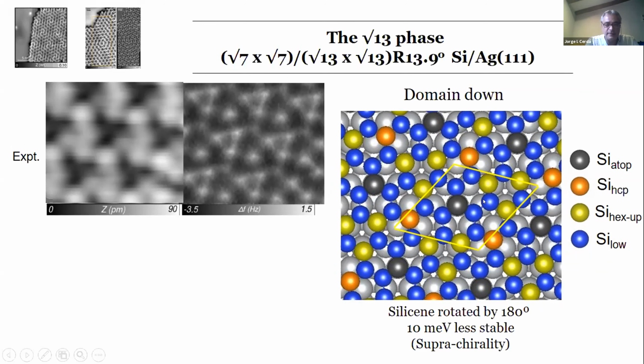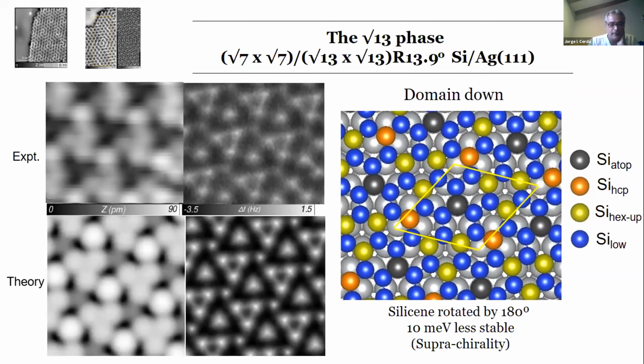And now we have, again, the silicon on top. We have these hexamers. Before they were around an HCP side, now they are around an FCC side. And now this single atom is sitting at an HCP, while before it was sitting on an FCC. So they're not exactly identical, but it really points to supra-chirality. Now we change the orientation of them, and they cannot be superimposed.